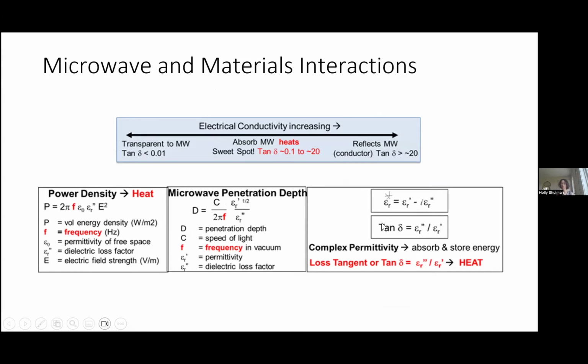The real part is where it can follow the field, align in the field, and add to the polarization. The imaginary part is the dielectric loss, that it's lagging. So it's not frozen in, it's trying to follow the field, but it can't quite make it. And that lag gives heat. It's like an internal friction, and it builds heat.